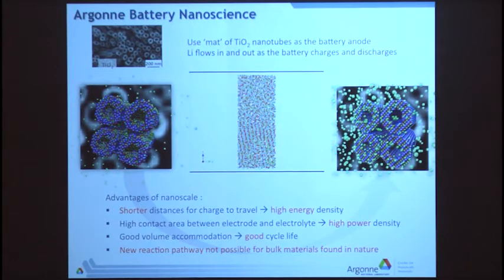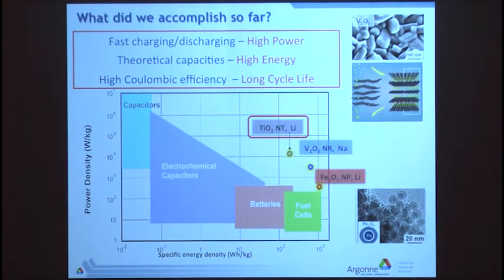It starts out very random, and then I hope you can see that we're starting to generate these lines of atoms. You're starting to generate a crystal structure. And by the time it's been fully charged, it's fully crystalline. It's a perfect lithium titanium oxide crystal structure, and this charges very fast and has a very high capacity. This was a really nice thing that was shown by experiment first, but we didn't really understand why. Then by theory we could put that together with the experiment and understand it. And why that's important is that we've now been able to add this data point over here, which is getting us up towards that top right-hand corner, which is where we want to be.